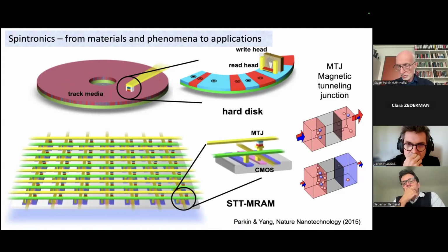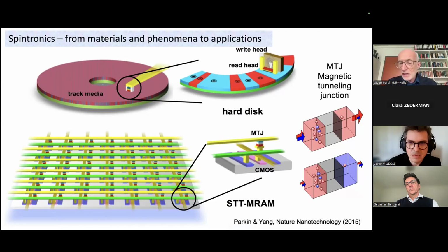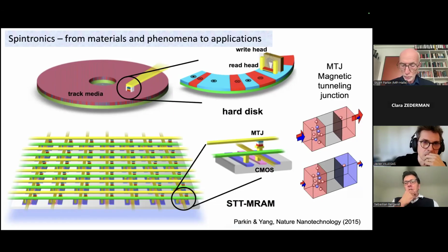So these are today used as sensing devices in a magnetic disk drive, and together the metallic version, the spin valve, and the magnetic tunneling junction enabled a 1,000-fold increase or more in the storage capacity of these magnetic disk drives. Those disk drives now have reached the end of their technology roadmap, and so an emerging technology is to use the same tunneling junction as a memory element where you store information in the direction of magnetization of one of these electrodes, blue and red as shown here. And in fact, this is something that we first proposed in 1995, and it was only in 2019 that this became a reality. You can now buy this magnetic random access memory from the major foundries all around the world.